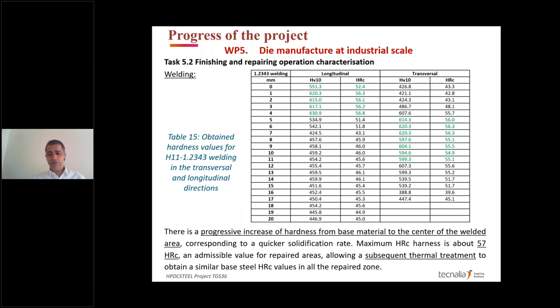And we checked the hardness. In the intermediate area there was an increased hardness, with values of up to 57 when we weld with the H11. So this told us that a subsequent thermal treatment is necessary if we make a repair with this H11 rod.